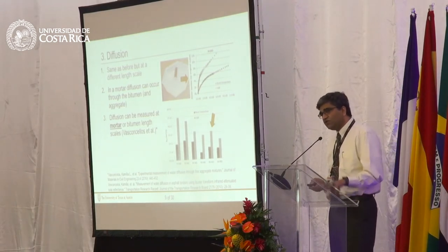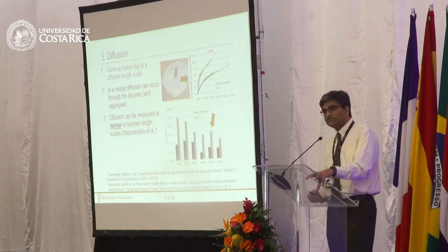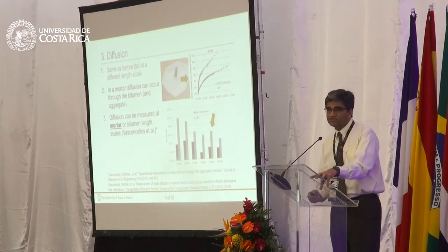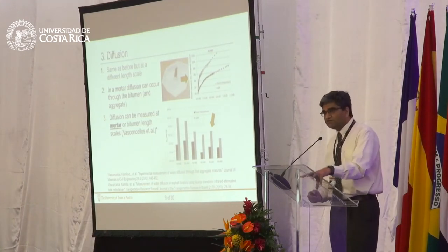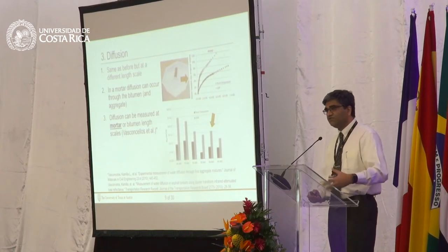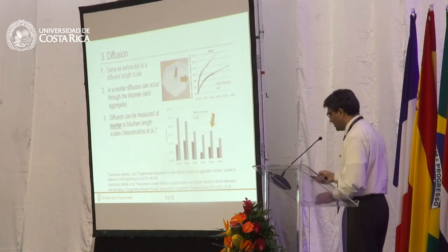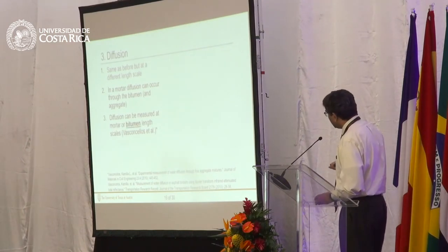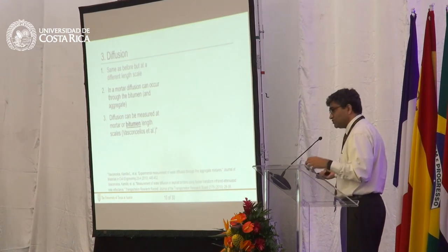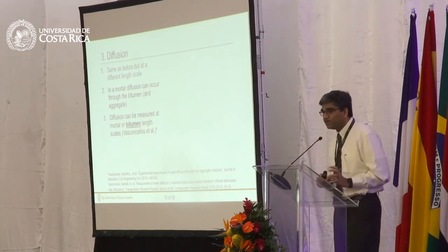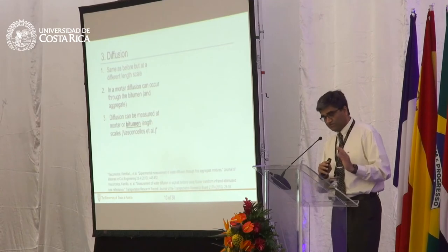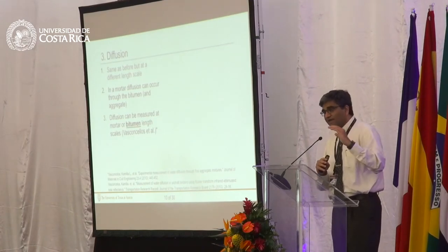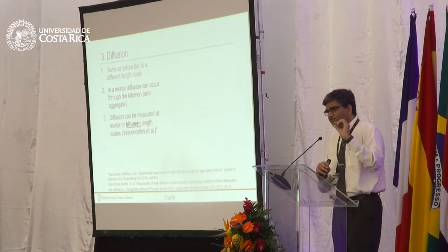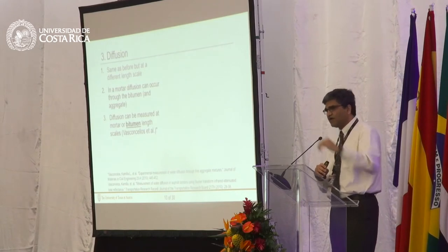It's a function of the type of minerals you use in the mortar. It is a function of the type of bitumen. Some kinds of bitumen have higher diffusivity and will allow moisture to get in faster. Others take time. Moisture also diffuses through bitumen. Mortar is a composite, and if you think about a composite, the moisture is traveling through bitumen. In very rare cases, if you have porous aggregate, the water will travel through the aggregate itself.